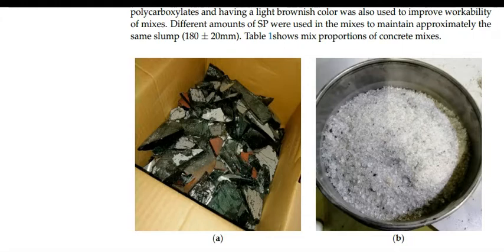The aim of this paper is to assess the flexural behavior of reinforced concrete beams with CRT content. Four mixes were prepared: a control mix CRT-0, and three mixes CRT-10, CRT-20, and CRT-30, containing 10%, 20%, and 30% of CRT glass waste by volume. The mix proportions were 1:2:4 for cement, fine aggregates, and coarse aggregates.